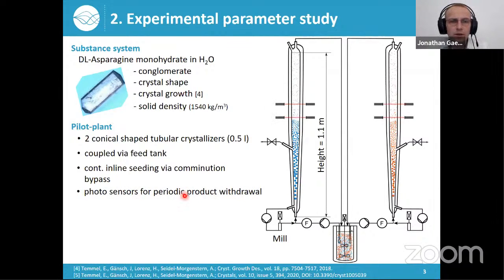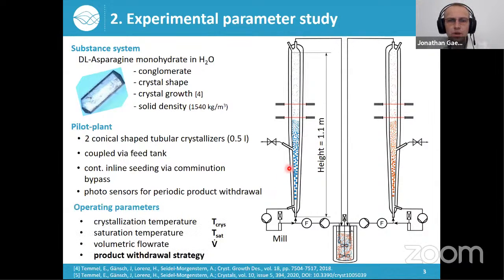Regarding the product withdrawal, due to the scale of our crystallizers, a continuous product withdrawal is not practical. That's why we are using these 2 photosensors to realize a periodic product withdrawal. And the operating parameters of this process are first our crystallization temperature, then the supersaturation, which we can set via the saturation temperature here in the feed tank, then the volumetric flow rate of our feeding solution, which we can measure and control here with our Coriolis flow meter, and also our product withdrawal strategy. So when and how often do we withdraw our product here at this product outlet?